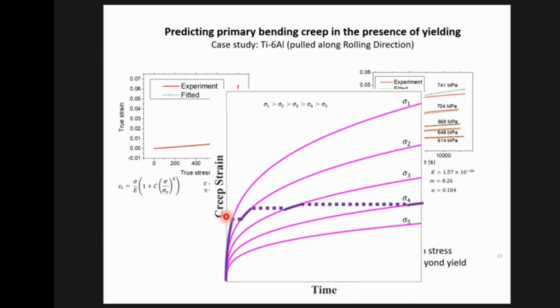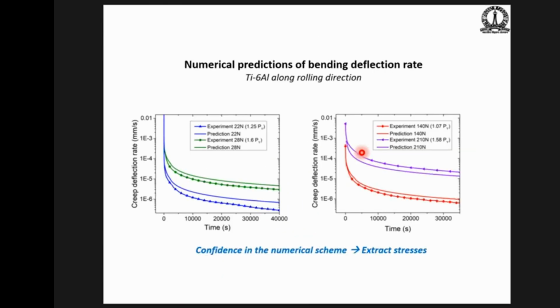So remember that when you do a creep test in bending, the stress is changing all the time. At a given point, the stress never reaches steady state. So this is not steady state strain rate, but steady state stress distribution, if you like. So you have to adjust the deformation rate at any point by moving from one creep curve at a stress of, let's say, sigma 1 to a changed value at sigma 2. And this is done iteratively for the entire beam in a self-consistent way, so that you balance the bending moment, whatever load you're applying, and you maintain strain linearity across the section. When you do that, you get a reasonable correspondence between the prediction and the experiment of the deflection. So the only thing you're measuring here is the deflection rate.